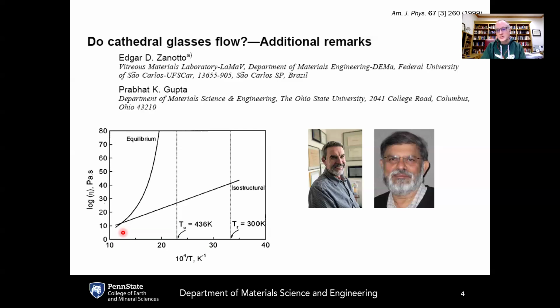And what happens is that the structure of that supercooled liquid gradually freezes into this solid-like glassy state. And when that happens, the viscosity curve no longer follows this equilibrium curve predicted by the VFT equation, but rather it departs from that and it freezes in to give this straight line here on this logarithmic plot. This is what's called an Arrhenius plot here that shows a straight line of the log of the viscosity versus the inverse temperature. And this is what he called the isostructural viscosity. Isostructural meaning that it is the frozen in structure. So when the structure becomes frozen in, the activation barrier for the viscous flow becomes frozen in, and that's what gives the straight line behavior here.